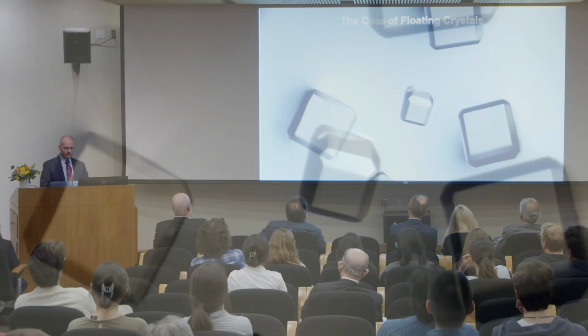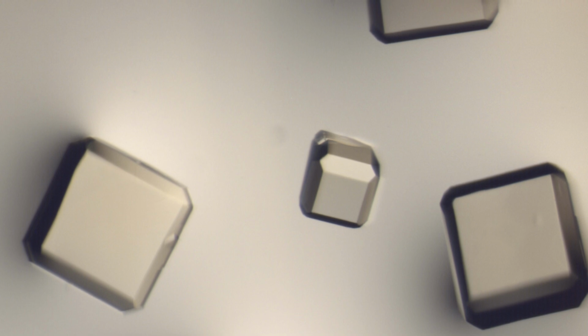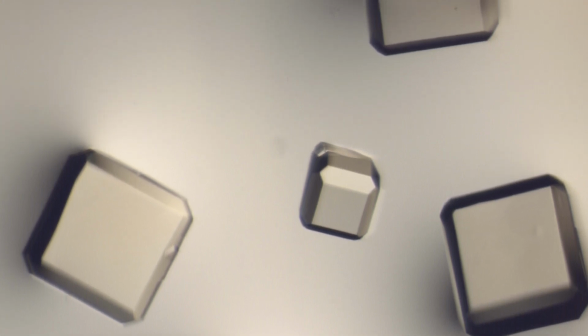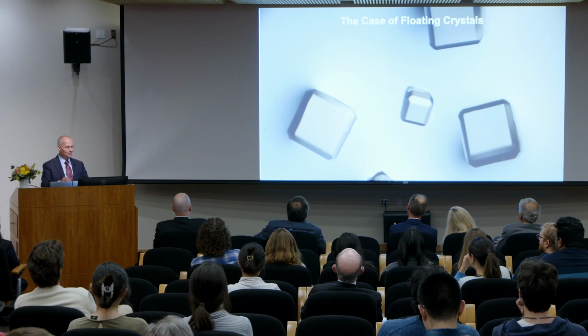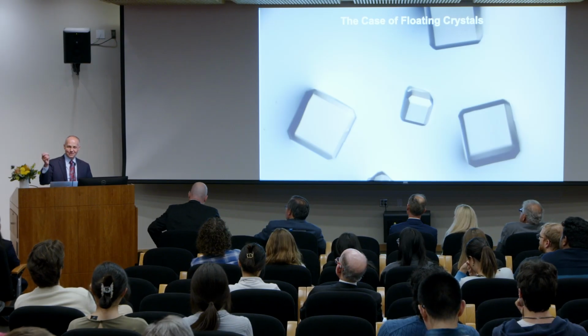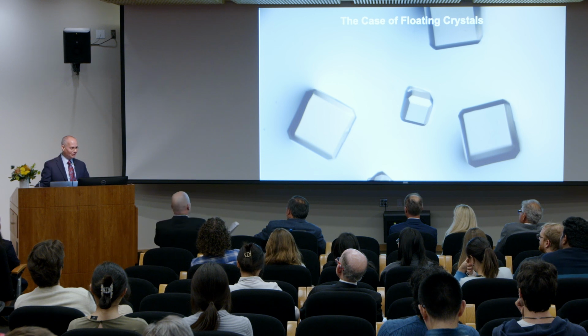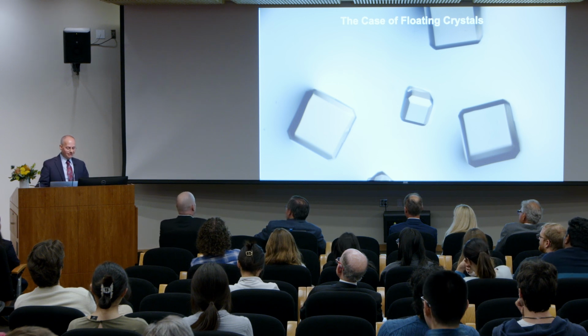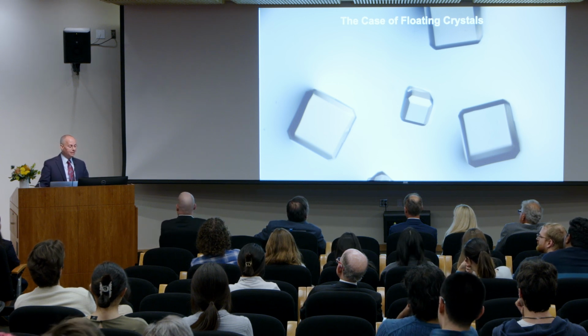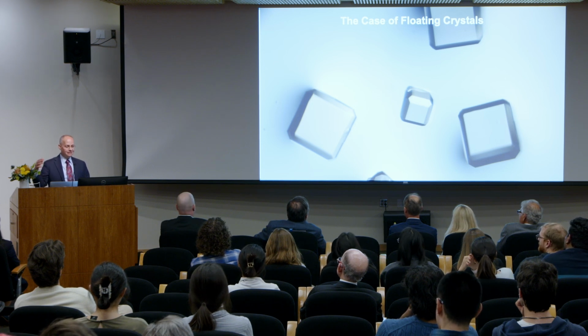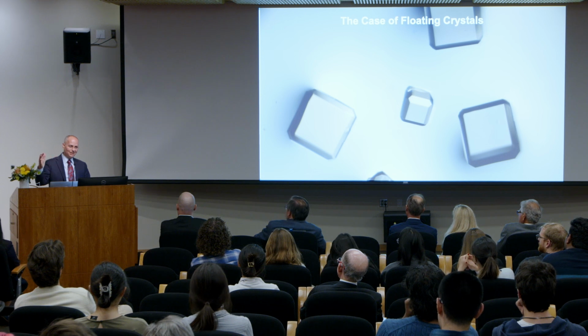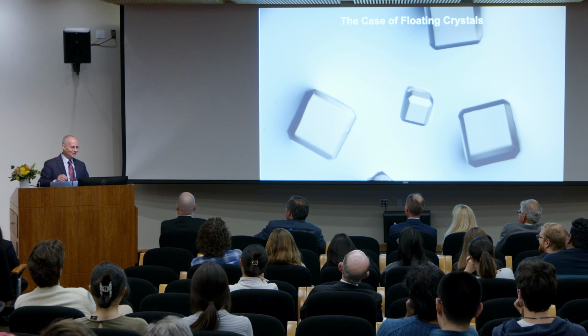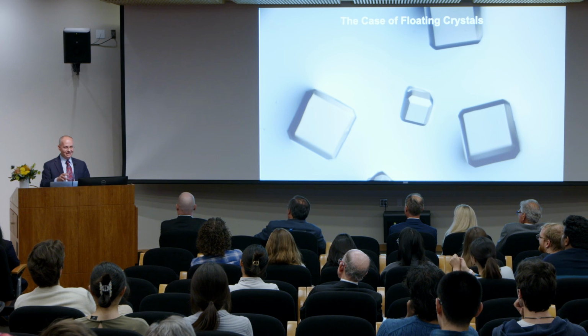And that is that the student that discovered this compound initially deemed it uninteresting. They looked at these crystals, they were in love with them, but they picked them out of the solution and put them on the diffractometer. And of course, they had lost their crystallinity because we didn't know they were filled with solvent because they were porous. So I was not hovering very far behind the student and said, no. You need to mount this crystal in its mother liquor or in the liquid. And that was